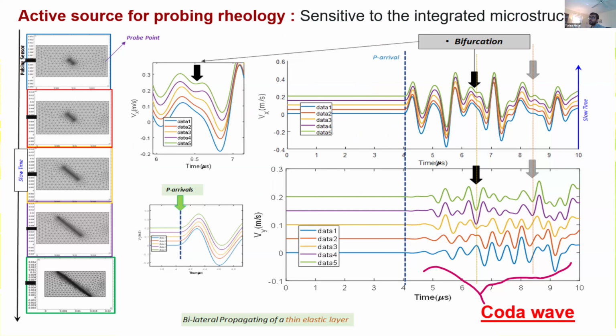To understand how sensitive coda waves might be to some of the internal structures of the medium, we've done some simulations in COMSOL, a 2D simulation. We have a pulsing sensor on the left and one probe point on the right. That's analogous to what we can do in the lab, for instance. In this case, the thing that's changing from the top to the bottom on the left-hand side is that we put in a damage zone, a region that has slightly different elastic properties. When we do the simulations, we look at what the probe point records, and that's shown on the right.